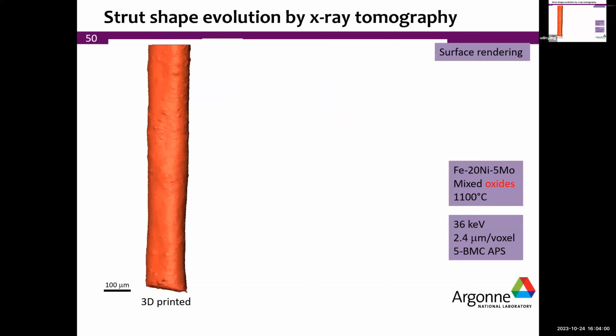The other thing we can do once we have high intensity tomography, this is now done at Argonne, is to do high intensity X-rays. We can do tomography. So we can do a full reconstruction of the material. We don't have the resolution, or we'll barely have the resolution to see what's inside. So the first thing we're going to do is kind of reconstruct that printed structure.